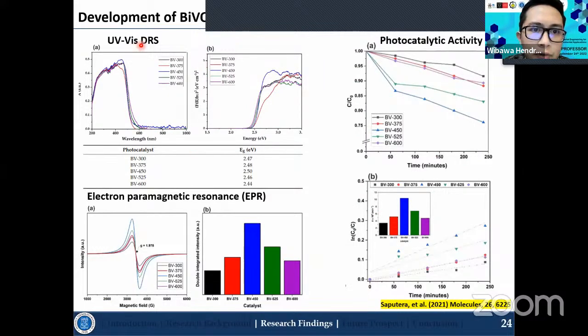So UV-vis diffuse reflectance spectroscopy, where we can calculate the band gap of the photocatalyst by using these characterizations, and it can be seen that the band gap of this photocatalyst is lower compared with the titanium dioxide. So it's around 2.4 until 2.5 electron volt, which indicated that this type of photocatalyst can be activated using lower energy or visible light energy.